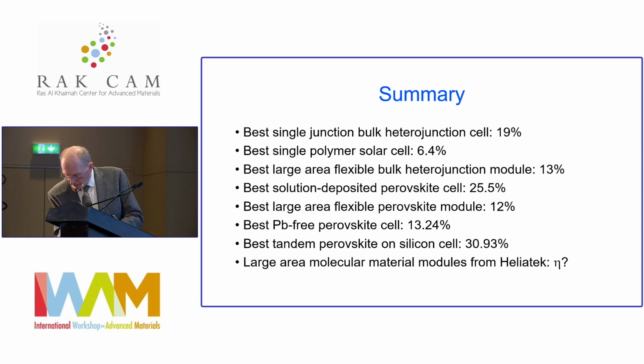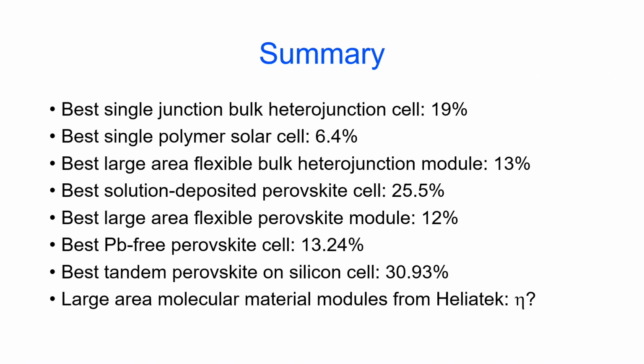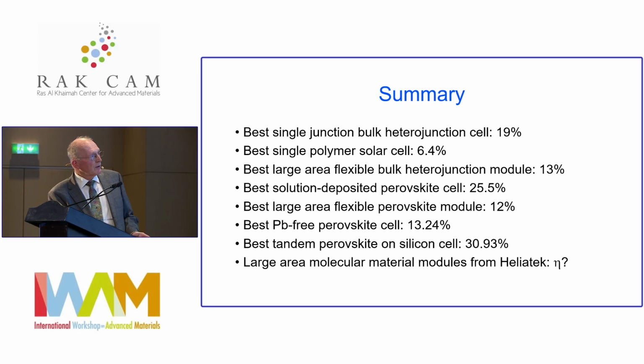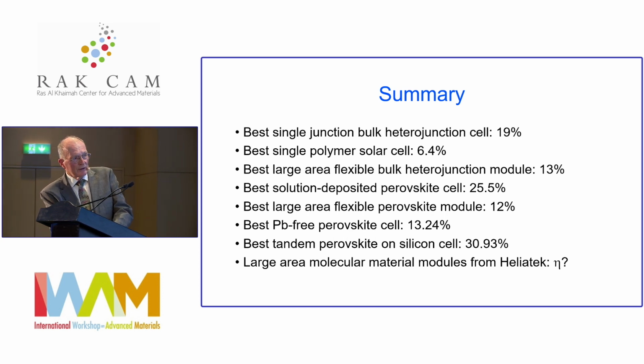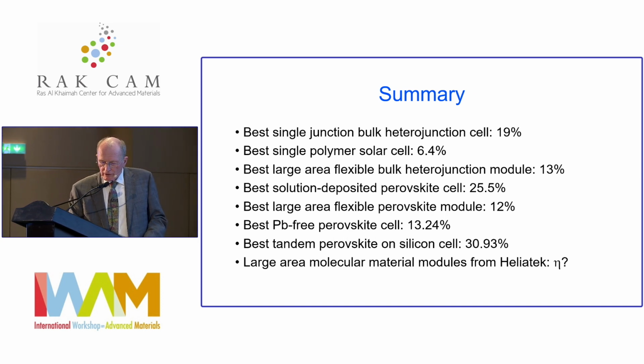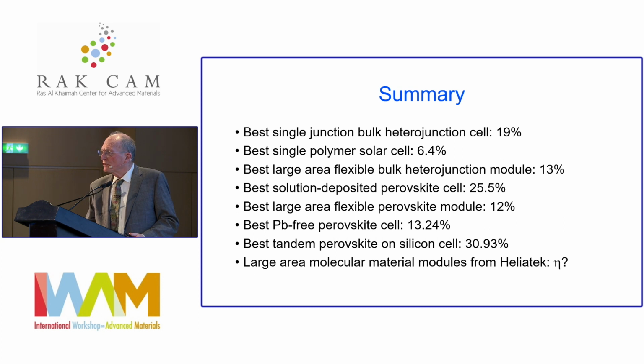But let me just summarize now what I've presented to you: the best single bulk heterojunction cells, 19%; the best single polymer solar cell, 6.4%; the best large area flexible bulk heterojunction module is 13%; the best solution deposited perovskite cell, 25.5%; the best large area perovskite module, 12%; the best lead-free perovskite, 13.24%; and the best tandem perovskite on silicon, 30.93%. And as I said, I don't have the efficiencies for Heliatek, but my guess, knowing what we do about the best organic materials, is it won't be much. It'll be between 10 to 15%.